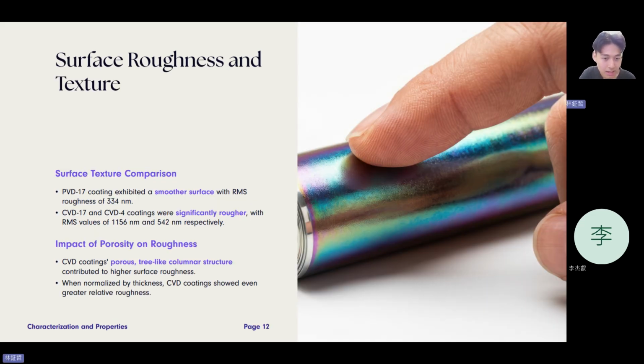Roughness. Next, we measured the surface roughness. The PVD 17 coating has a smooth surface texture. Its roughness value is 334 nanometers, but the CVD coatings are much higher. The CVD 17 has a roughness of 1156 nanometers, and the CVD 4 is 542 nanometers. The reason for this high roughness is the porous tree-like structure of the CVD film. Even if we divide the roughness by the thickness, the CVD coatings are still much rougher than PVD.